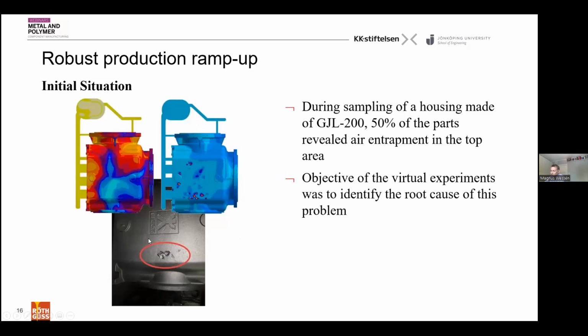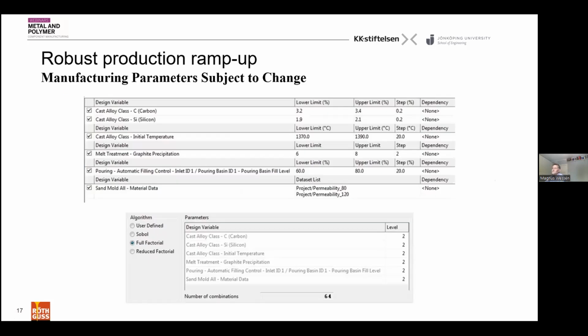So if this is the recasting, and here you see the air pressure as opposed in the simulation, and you can see that this is a cold area. So when the melt fills up, this gets quite cold. So that's a risk, cold flows here, and you have this trapped air, process problems. So the object of this one was to run a number of virtual experiments to identify the root cause of this problem. And there are many things which can affect this.